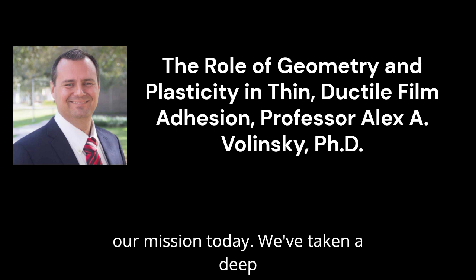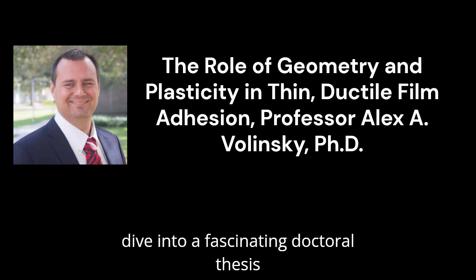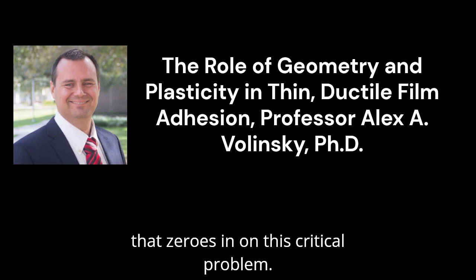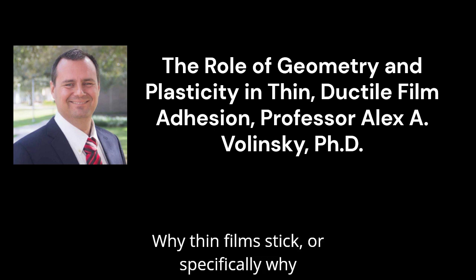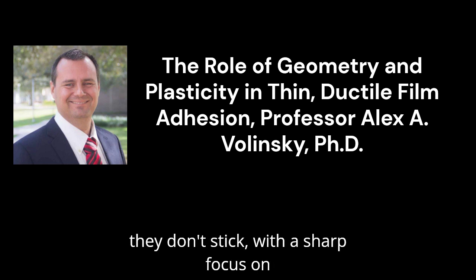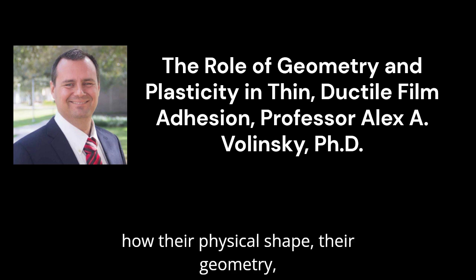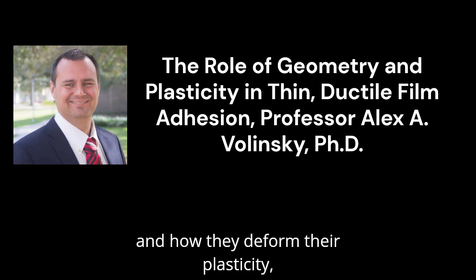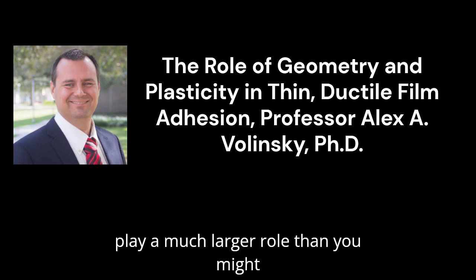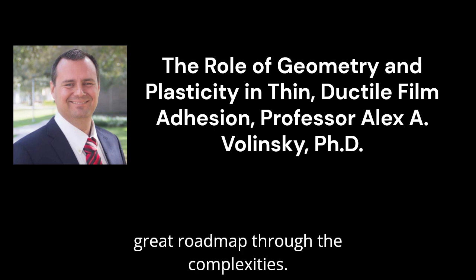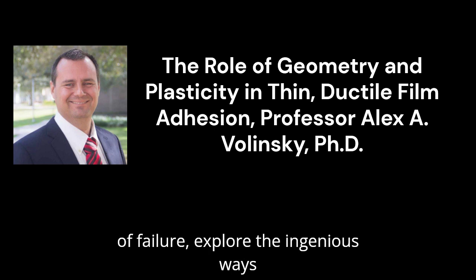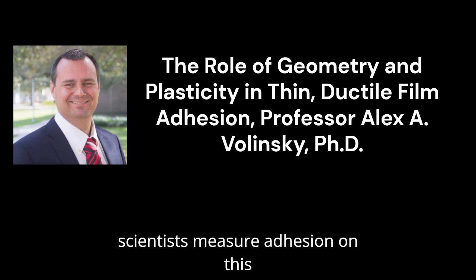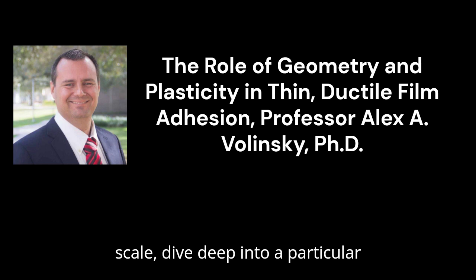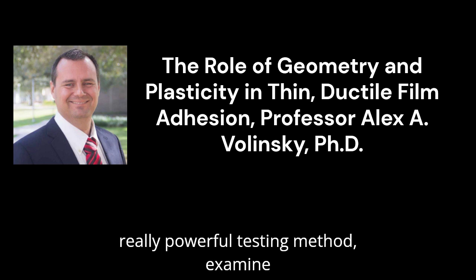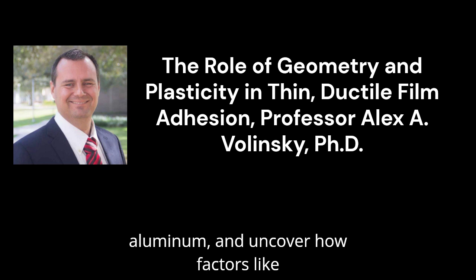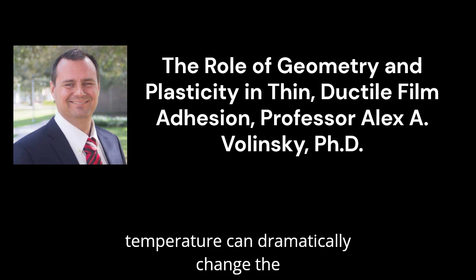So that's our mission today. We've taken a deep dive into a fascinating doctoral thesis that zeroes in on this critical problem. Why thin films stick, or specifically why they don't stick, with a sharp focus on how their physical shape, their geometry, and how they deform, their plasticity, play a much larger role than you might initially think. This work provides a great roadmap through the complexities. We're going to unpack the core mechanism of failure, explore the ingenious ways scientists measure adhesion on this scale, dive deep into a particularly powerful testing method, examine specific materials like copper and aluminum, and uncover how factors like temperature can dramatically change the picture.